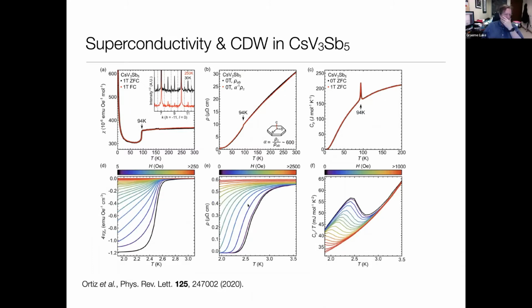So the first thing you see upon cooling down from room temperature, if you measure the resistance or the susceptibility or the specific heat, is a very clear phase transition at 94 Kelvin. You see it in all three techniques. And when you do a scattering experiment, in addition to the regular Bragg peaks indicating your crystal structure, some superlattice peaks appear as well, which tells you that you've got some sort of charge density wave forming in the material. So there's a lowering of the symmetry at this point.